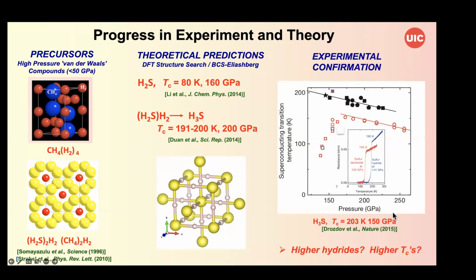And of course, this work was confirmed rather quickly by my colleague Mikhail Eremets and his group with very nice measurements of the pressure dependence of this, as well as the isotope effect, indicating this is indeed essentially conventional superconductivity. And the remarkable finding is that this is in very good agreement, both in terms of the structure, the Tc, and the range of stability, with what came out of the DFT calculations. But what about higher hydrides and still higher Tcs?